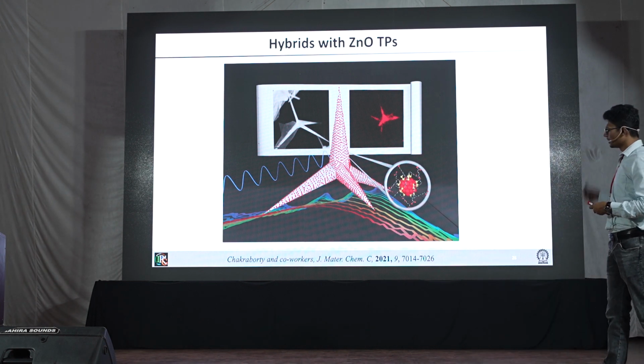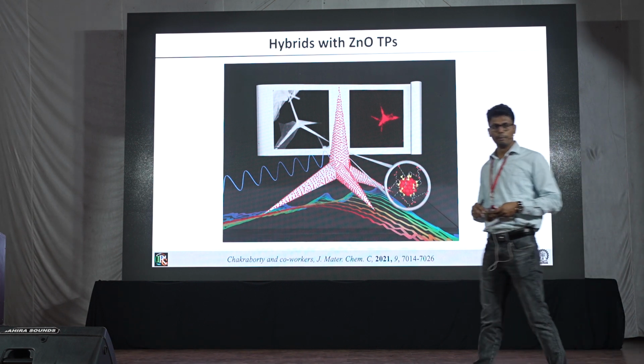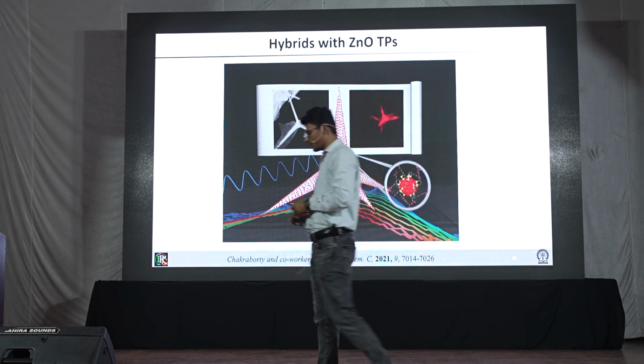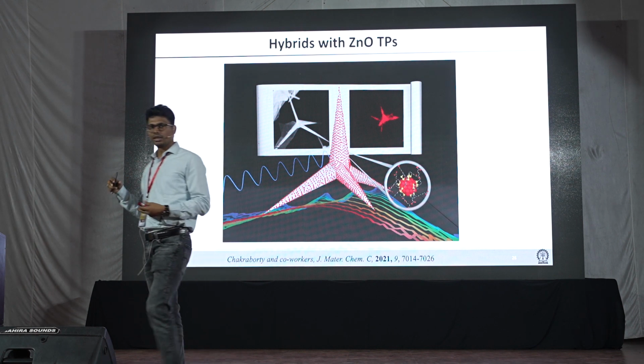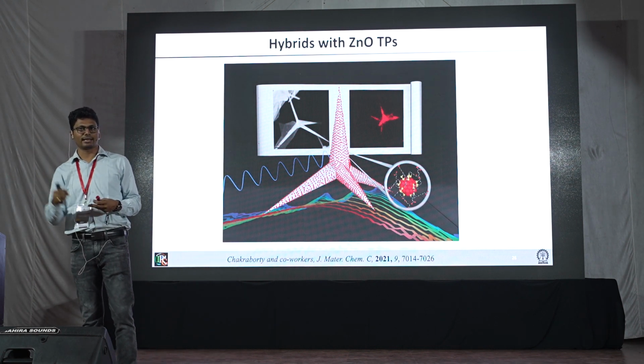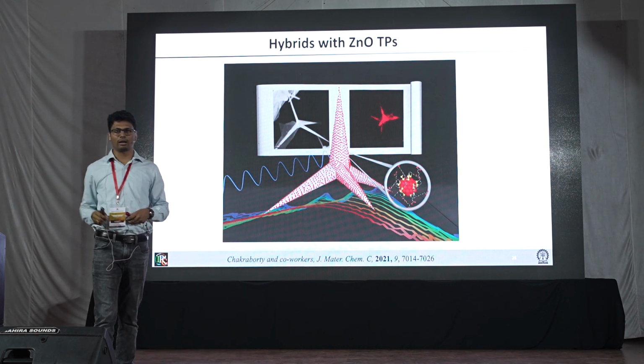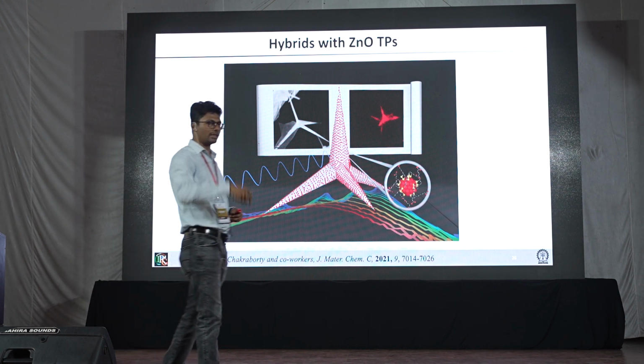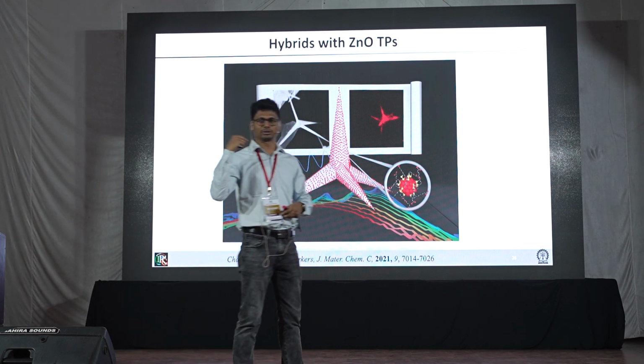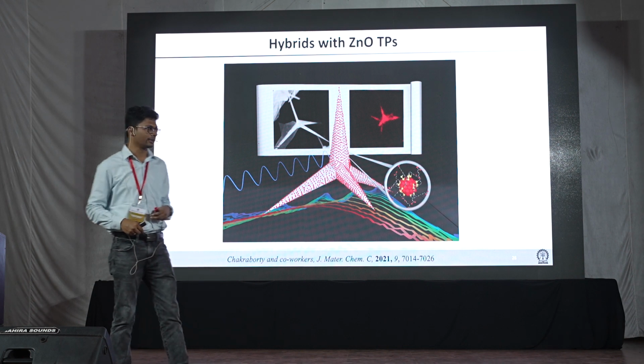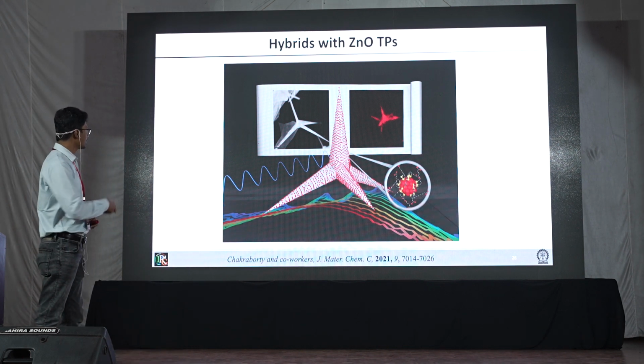So one of them is here, which is ZnO tetrapod. So zinc oxide basically has a very nice structure. You can anchor clusters. They have a porous size as well. And the clusters have a free carboxyl group, which can anchor on the zinc. That's basically a very strong binder for the ligand that you can add. And that leads to nice structures.